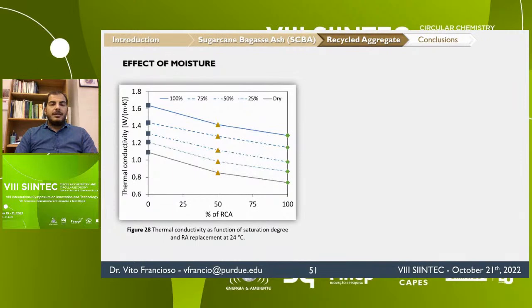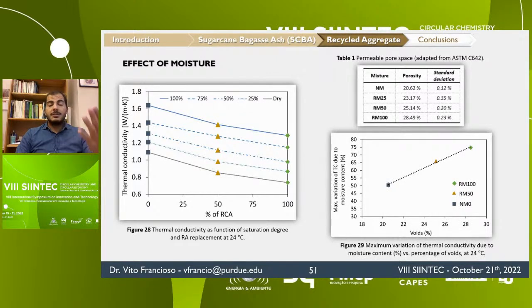Figure 28 shows the thermal conductivity as a function of the recycled concrete aggregate for each saturation level. The higher the recycled concrete aggregate replacement, the lower the thermal conductivity, as expected. Also, the higher the saturation level, the higher the thermal conductivity. However, more importantly, if we observe the variation of thermal conductivity between the dry and saturated state, we see that the higher the permeable pore space, the higher the variation. So the higher the recycled concrete aggregate replacement, the higher the variation in thermal conductivity between the dry and the saturated state.